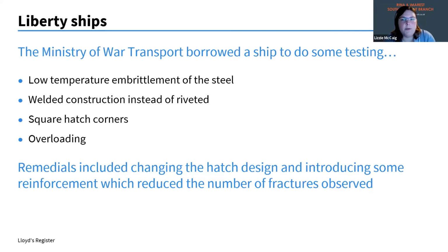And because of the quite poor design of the hatch corners, they had square hatch corners, and they also had weld seams located close to the hatch corners. That also meant that you had stress concentrations at that hatch corner that then went into the weld, and then went all the way down the weld and all the way around the ship.